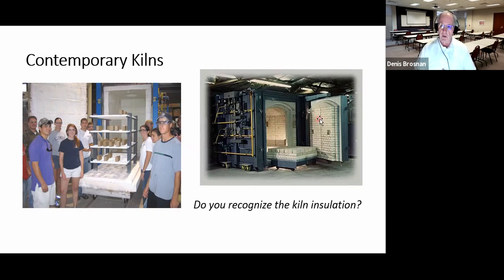I hope you do. The insulating material or refractory material is different in these two kilns. The one on the right has fire bricks. You can see the brick patterns here on the inside of the kiln and the door of the kiln, which swings shut, and the car. Yet in my laboratory kiln, you can see that it's fiber ceramic insulated. Also the kiln car is fiber ceramic, and these posts hold saggers or plates which hold the ware suspended into the kiln atmosphere.